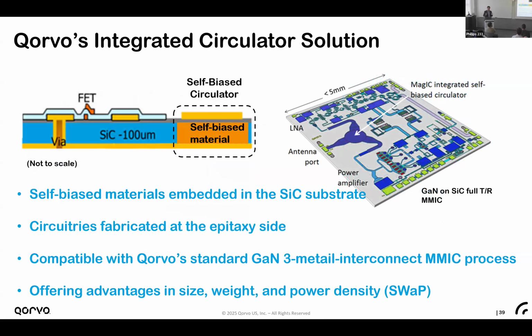So this is our approach in the DARPA M3IC program. We try to etch a pocket on the backside of our silicon carbide substrate. The substrate is thinned down to 4 mil, 100 micron thick. We are using this technology together with our GaN 1.5 technology node, which is 150 nanometer gate. So the substrate thickness is 100 micron there.